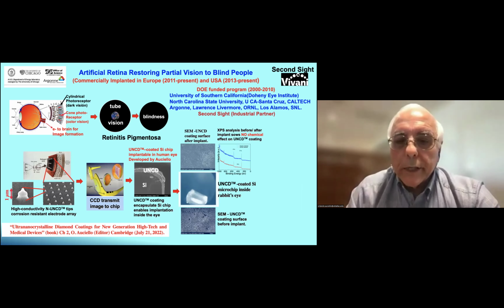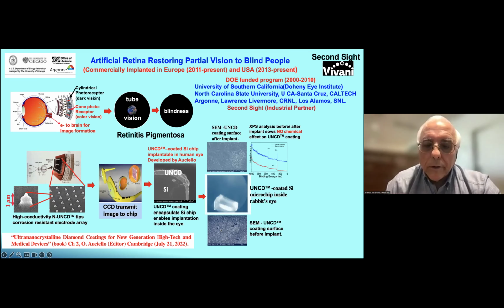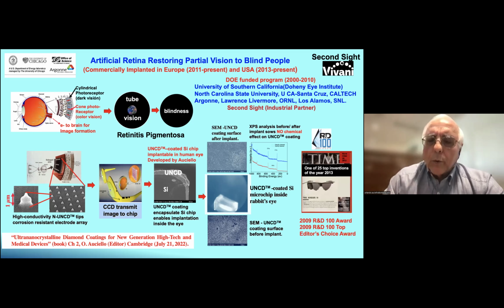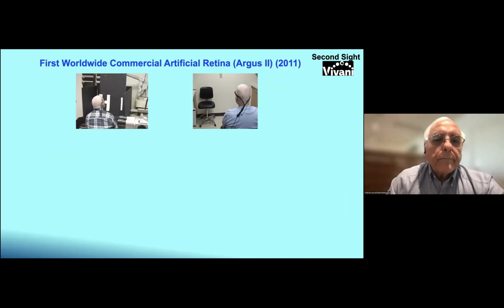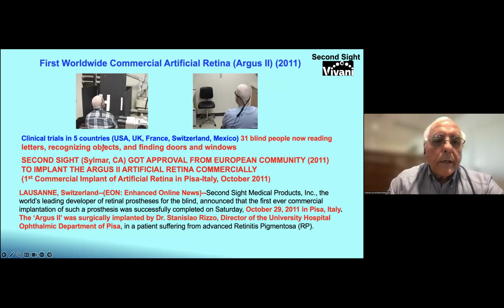So we demonstrated UNCD coated silicon chips implanted in rabbit eyes for about 3 years, SEM on the top before implantation, on the bottom after implantation. XPS analysis showed total inertness of the UNCD coated silicon chip. Our device, called Argus 2, was named one of the top 25 inventions of 2013 by Time magazine. We did 10 years of clinical trials in the USA, UK, France, Switzerland, and Mexico, implanting 31 people.